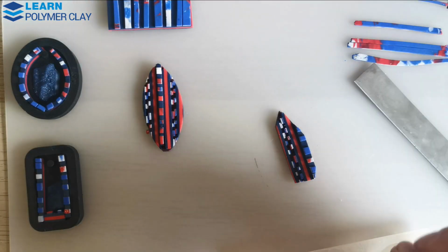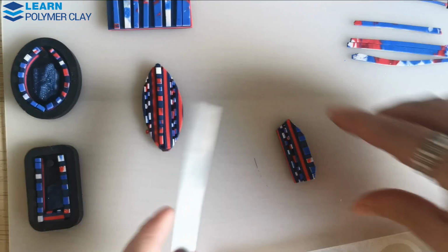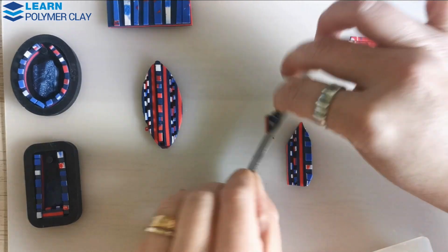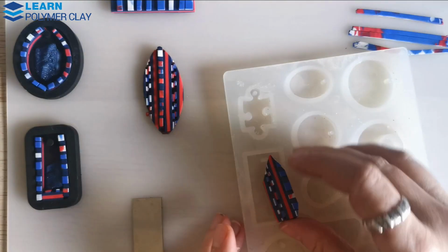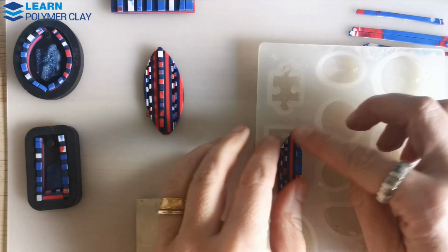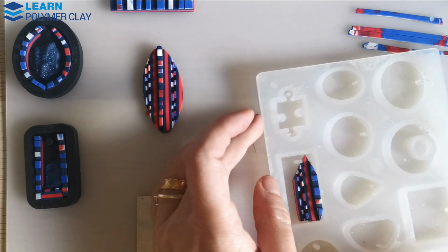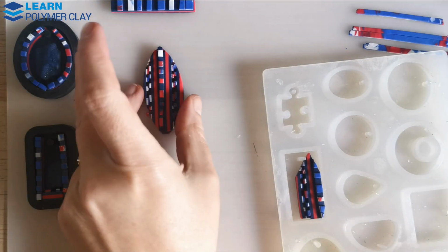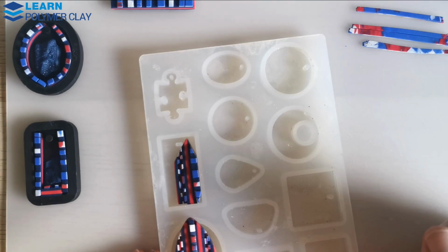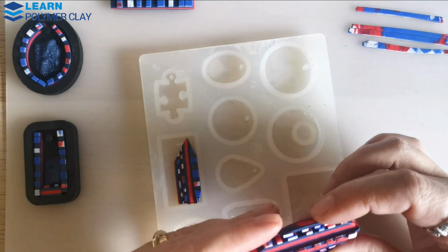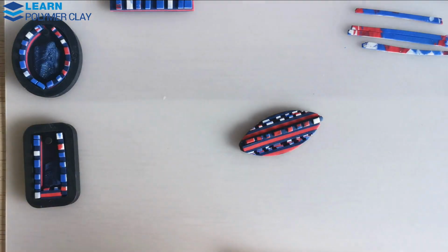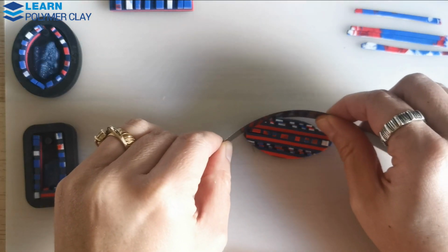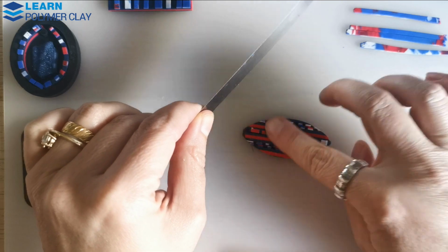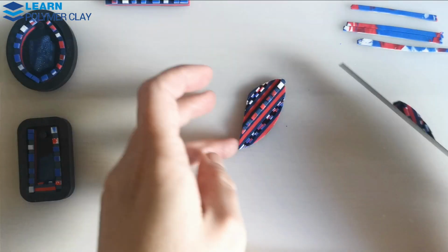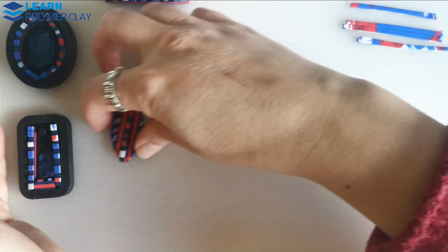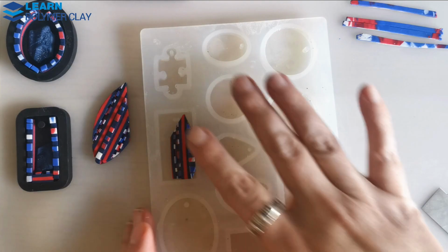And then I decided to use a different mold, a transparent one, and the curing of the UV resin went perfectly for the pieces that I put in this mold. And for the pieces that I cured under the UV lamp in the black mold, I had to cure them again because they did not cure properly the first time. So when working with polymer clay, there are always things you can learn or improve.